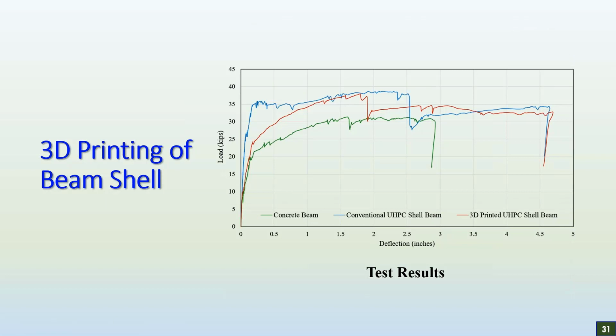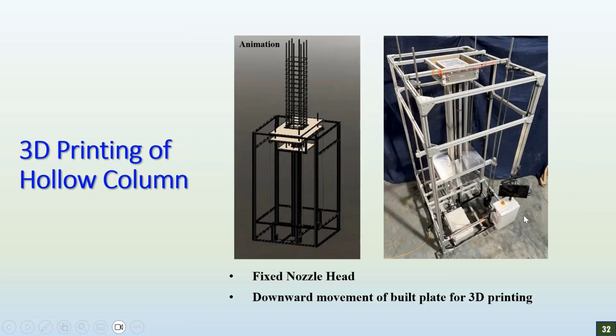If we see the difference in the load deflection curves for all three specimens, we can see that the cast in place specimen and the 3D printed specimen both exhibited a high load carrying capacity as compared to the concrete specimen. Both of these specimens exhibited approximately 20% more strength and approximately 40% more ductility. Now, this 3D printed beam specimen did not have any reinforcement inside the UHPC shell.